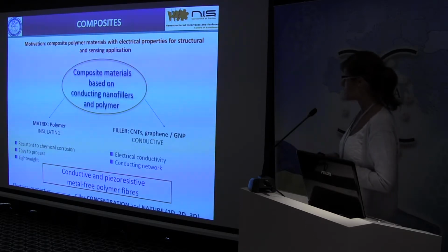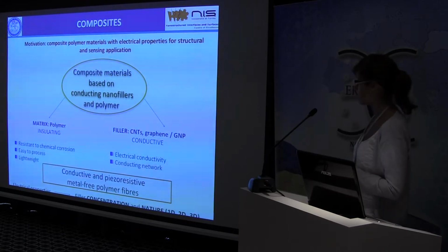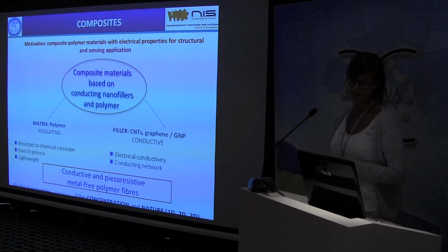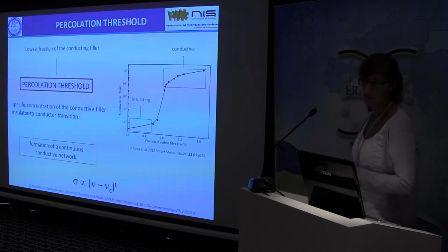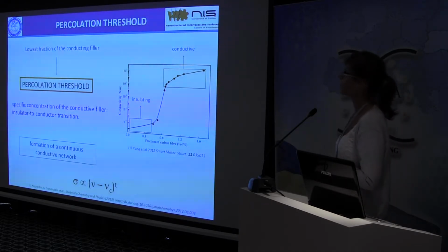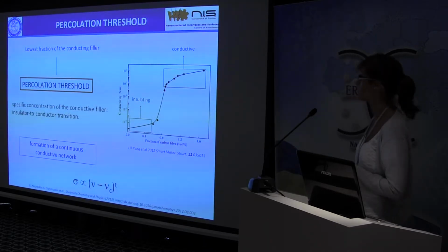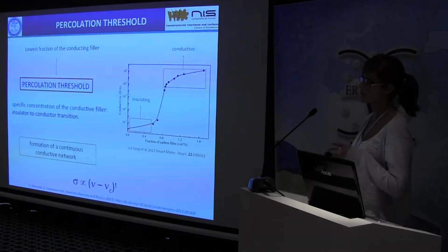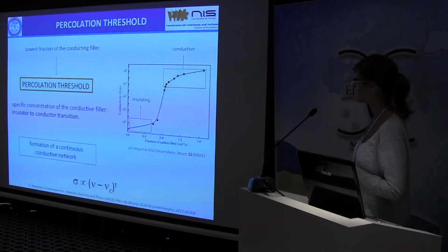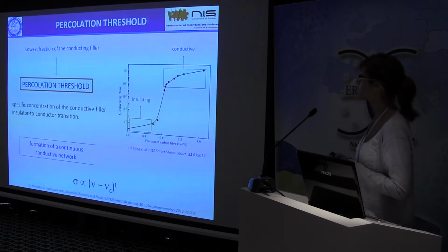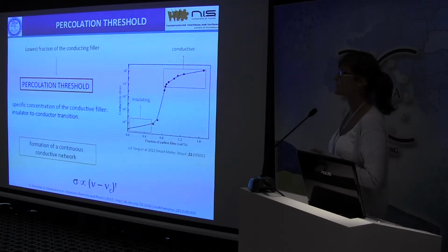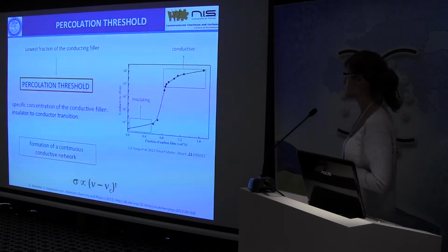So we realized a conductive and piezoresistive metal-free polymer fiber whose properties mainly depend on the nature and the concentration of the filler. So it is very important to know how much filler I have to put in the composite to have electrical conductivity. So it is important to define the percolation threshold of my composite, which is the lowest fraction of the conducting filler at which the composite begins to show electrical properties.